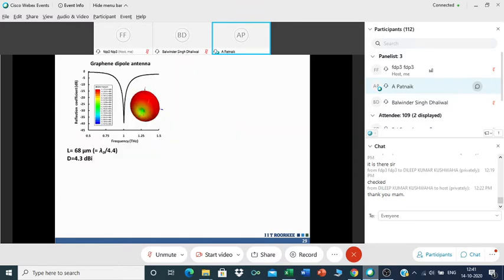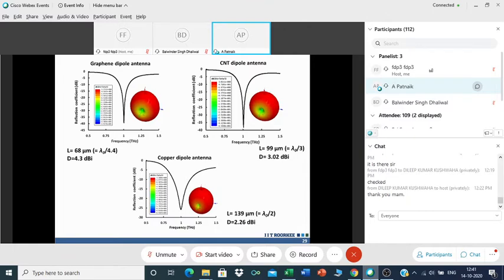So in the next step, what we did is we designed all these antennas for 1 terahertz frequency. Okay, we designed all these antennas for 1 terahertz frequency. So by simulation, in a trial and error method, we fixed the size of these antennas so that all the three antennas will resonate at 1 terahertz frequency. And we found that the physical size of the graphene antenna is less compared to the other two. And you can see the results for these antennas.